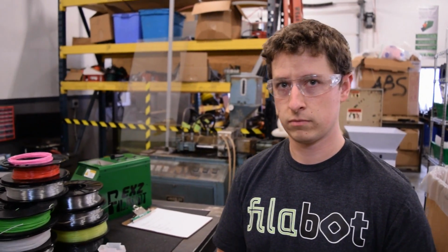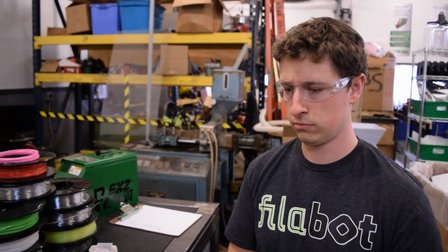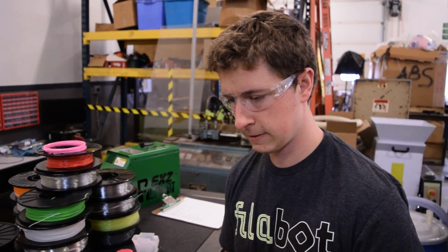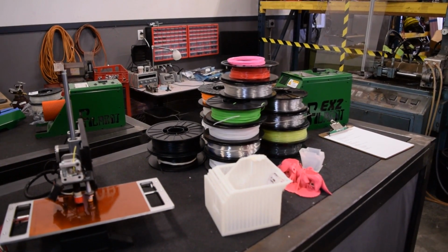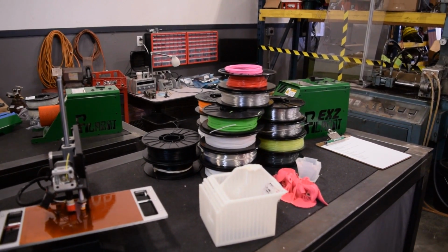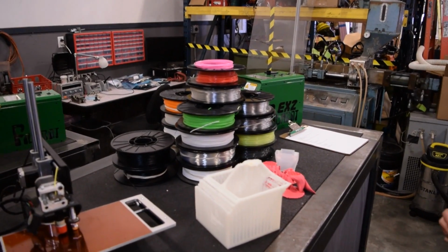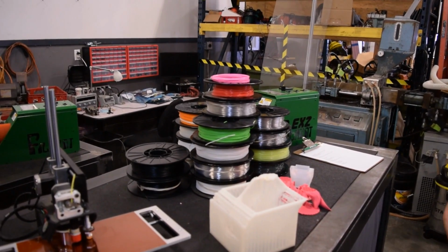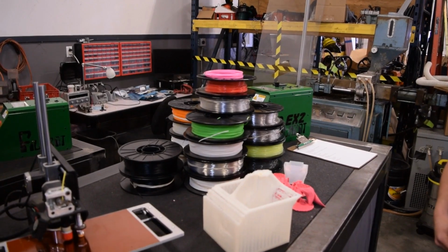Also, if you're mixing in colorants, sometimes, if your temperatures aren't right, your colorant doesn't mix very well, and you can have clumps of colorant that's not melted all the way. If it's the wrong colorant for the type of polymer you're extruding, that can clog your nozzle too.